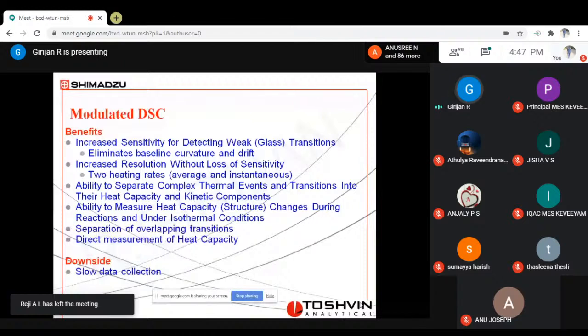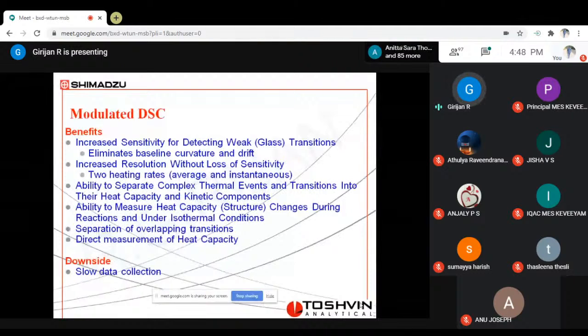So in a nutshell, modulated DSC benefits: increased sensitivity for detecting weak transitions. Sometimes these weak transitions may not be measurable in a normal DSC, but we can conveniently and sensitively measure them using an MDSC technique. It eliminates baseline curvature and drift. Increased resolution: we can get wonderful resolution without loss of sensitivity, so you are able to maximize sensitivity as well as resolution together, which is not possible in a normal DSC. Ability to separate complex thermal events and transitions into their heat capacity and their kinetic components.